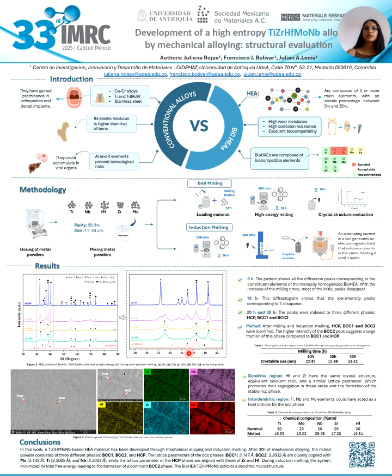The disappearance of these peaks suggests that some phases or components of the sample have been reduced, eliminated, or transformed into new phases. In addition, the disappearance of the diffraction peaks indicates the start of the formation of a solid solution phase. Now, I will focus on the pattern corresponding to milling for 10 hours.